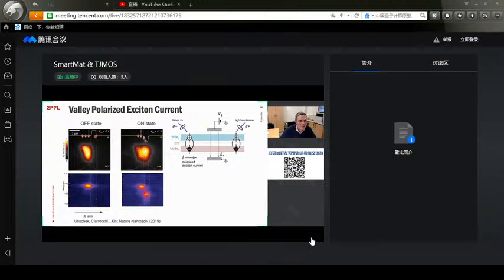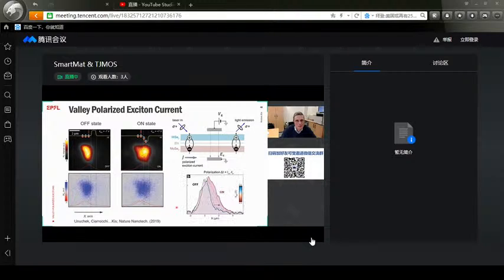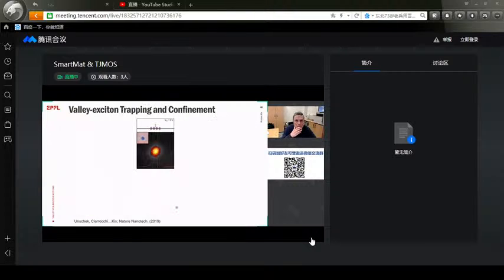So we can introduce a potential barrier that blocks the diffusion of excitons, and we can create a potential dip that's going to cause these excitons to fall in and lower their energy. And all of this is spin polarized. So all these currents and motion of excitons is also valid for spin polarized excitons.